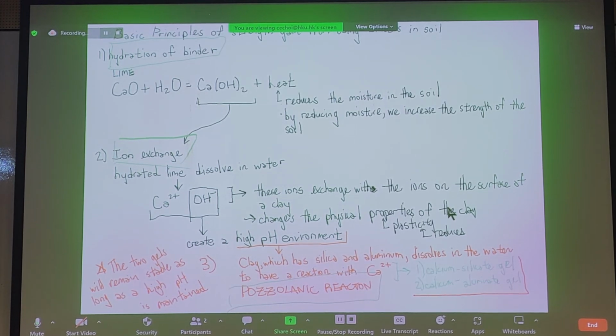So the first is if you hydrate a binder, you generate heat. Heat will reduce the moisture in the soil. By reducing moisture, we get strength. By hydrating the binder, you create ion exchange between the clay and the hydrated binder, which is the hydrated lime in this case. It changes the pH in the environment, changes the physical properties of the clay, and ultimately, this leads to pozzolanic reactions to get gels, right? You get two types of gels because clay has silicate and silica and aluminum. So these are the three main mechanisms.